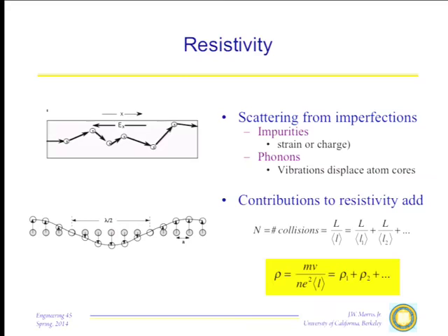How is that? Well, that's because, remember that our mobility is governed by scattering within the material. The electron is accelerated, it scatters, accelerated, it scatters, accelerated, it scatters. So what can it scatter from? And that will determine what the resistivity is. It can scatter from several things. One thing it can scatter from, well, it scatters from imperfections in the lattice.